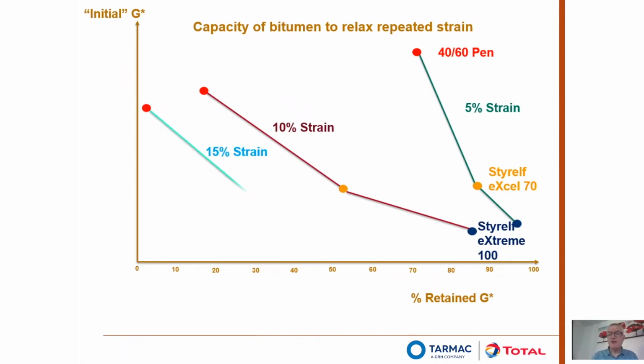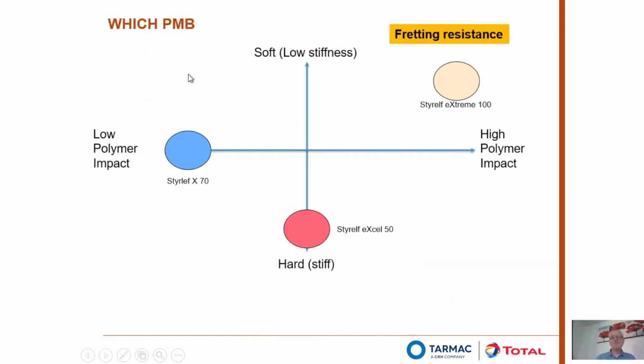If we move then up to 15% strain, the differences are exaggerated even further. So what that illustrates is that the Styrelf eXtreme 100, at the high end of the polymer impact, can cope with the repeated strains. In other words, it's good in fatigue resistance, much more so even than the Styrelf X70, and definitely more so than the 40/60 Pen.